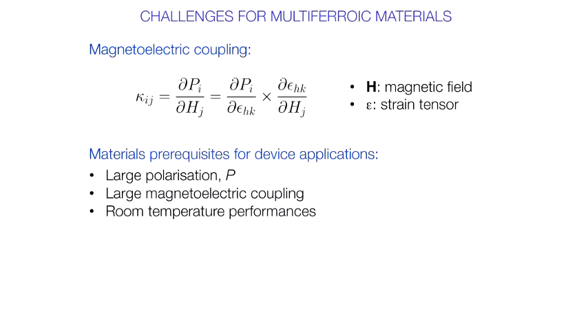Of course, the path towards commercialization is long. But I give you this example to fix the ideas, which are the possibility of controlling magnetic domains by an electric field, and which are the perspectives in terms of applications. OK, this is just the vision. But now the challenge is very severe for multiferroic materials, because you need to have a strong magnetoelectric coupling. And the strong magnetoelectric coupling means that it is sufficient to have a small electric field or a small polarization to change the magnetization, or vice versa. You need a small magnetic field in order to switch polarization.